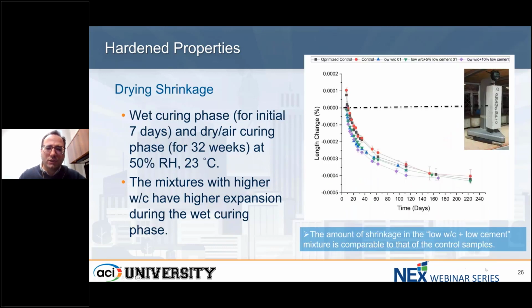We looked at the drying shrinkage as a dimensional stability performance criterion. So the approach we took here, we cured our samples, our beams, for 7 days in wet condition. And after that period, we air cured the systems inside the environmental chamber at controlled conditions, 50% relative humidity and 23 degrees Celsius temperature for 32 weeks. So the results are shown at the right side.